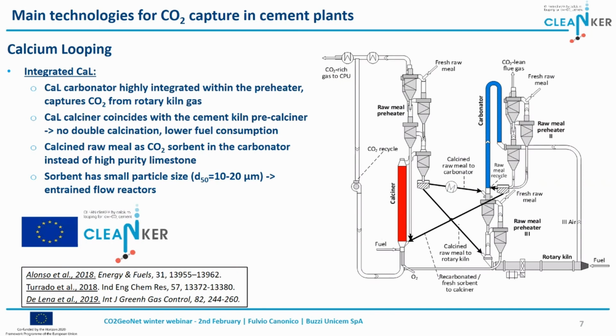What is the more recent development of this solution is integrated calcium looping. So with the idea to combine the calcination that is happening during the production of clinker at the cement plant with the calcination needed for producing the calcium oxide to be used in the calcium loop. So the idea behind the clinker project is exactly to test this solution at the cement plant. So to try to integrate the calcium looping in the production of the clinker, try to optimize the heat, so to use the heat of the cement plant for operating the carbonation. The carbonation happens at 650 degrees. And also to use the calcium oxide, which is used for the production of clinker.